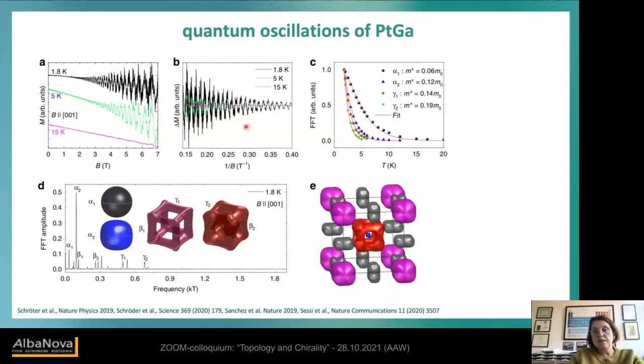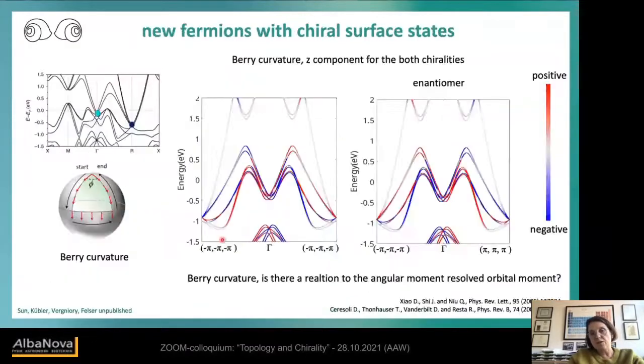And the quantum oscillation tells us exactly how good the agreement is between the calculation and the experimental measurement from a different perspective. And we just recently did more on the quantum oscillation together with Philip Moll, and we find a very, very interesting effect going beyond the simple interpretation of the Fermi surface.